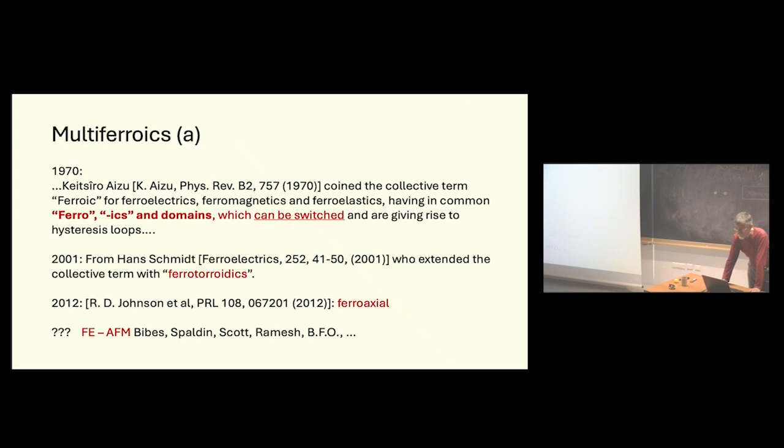So we have 212 species of macroscopic symmetry breaking. I was playing with groups which are not depending on time reversal. If you do it with time reversal point groups, magnetic point groups, then it's a little bit more of them, actually 1602, but I will not bother you with them. What is interesting now, let's think how many types of ferroics we have.